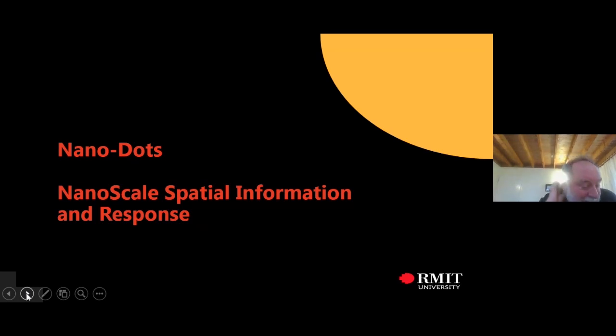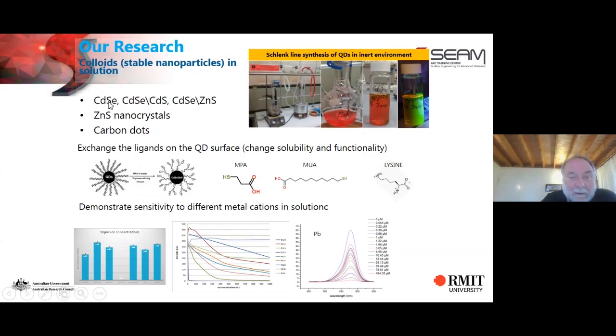Next area, just to tack on: I mentioned before, all our sensors to measure corrosion are actually not measuring corrosion of the metal itself, but they're measuring corrosion of a physical sensor adjacent to the metal. One way we began to address this was by developing nanodots. A nanodot might be a semiconductor dot like cadmium selenide, zinc sulfide, or carbon dots. Basically, these dots fluoresce at particular frequencies, and when particular metal ions come in contact, that fluorescence drops. There are particular ways to sensitize these dots for particular metals, but basically we could use the fluorescence of a dot to measure metal ion concentration.